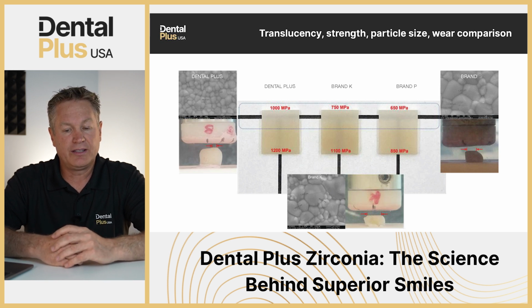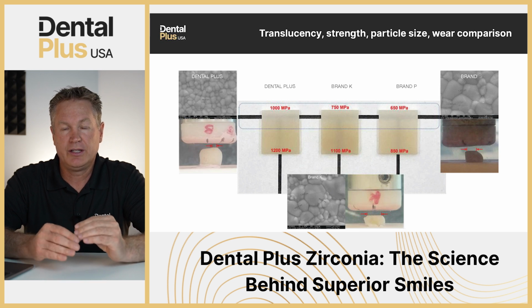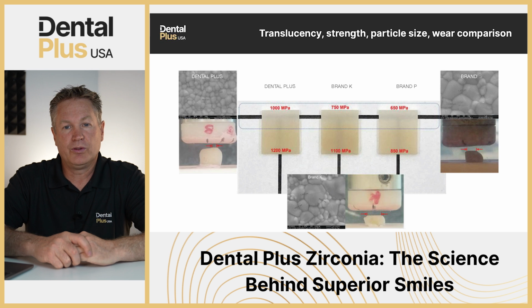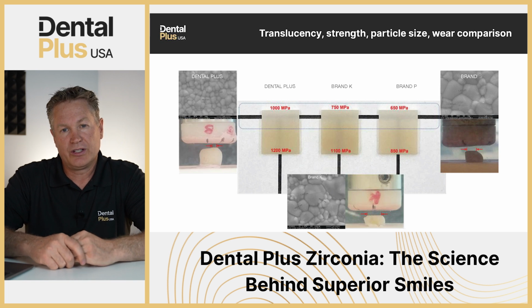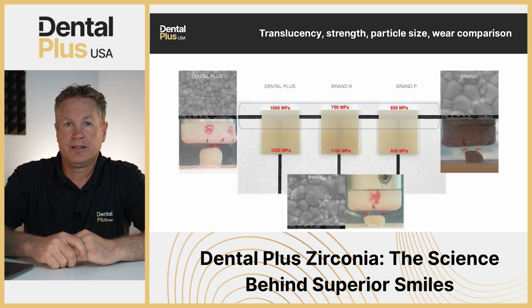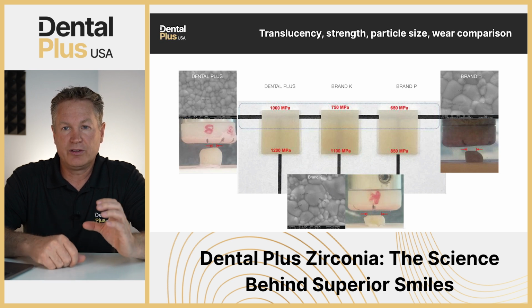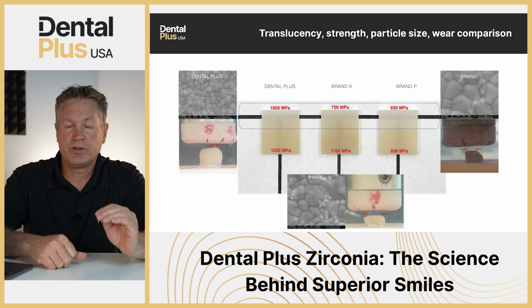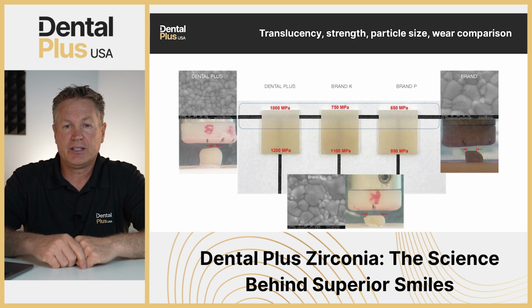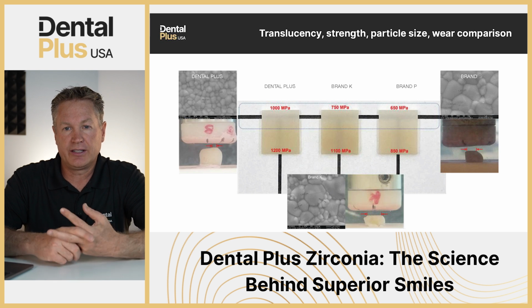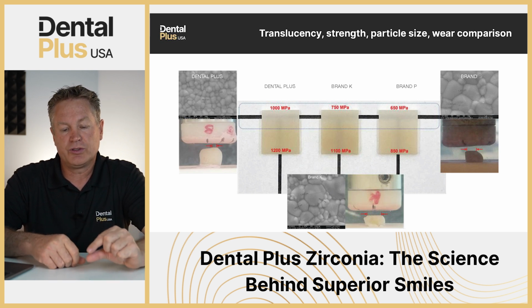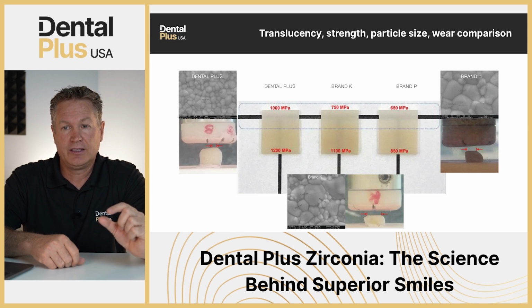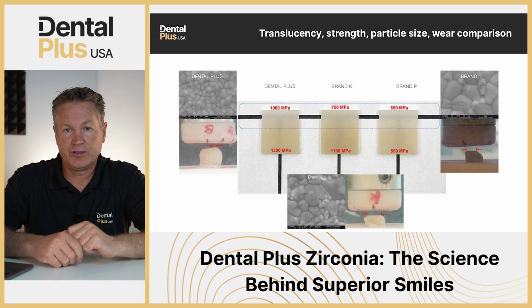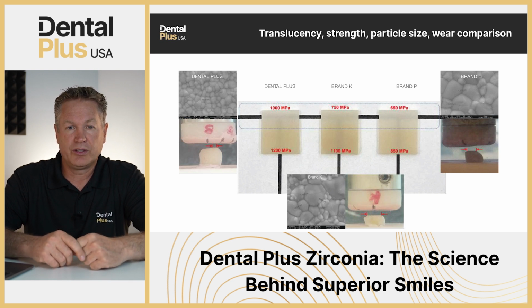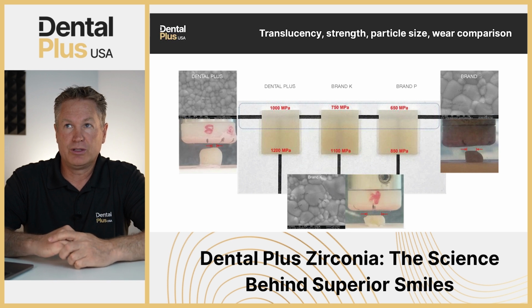And so that helps to create a stronger zirconia that has more translucency without adding more yttria to it. Typically when you add more yttria, you get more translucency, but you also get lower strength. With this method, you still get really great strength, but you also get great translucency without adding extra yttria to it. So you get the best of both worlds. You get great translucency and you get great strength. So that ratio between, say, the gingival side of the zirconia up to the incisal side is only 100 to 200 megapascal difference, compared to many other types of zirconias that have a lot bigger ratio between those two.